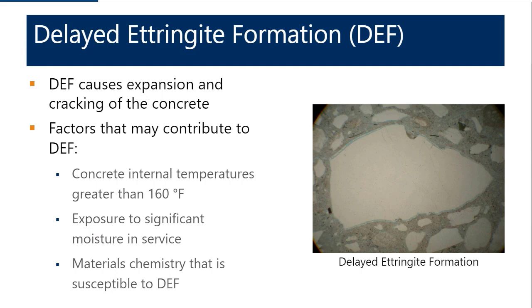So if temperatures exceed the specified limits, usually the next steps are to evaluate the risk of DEF. And that can be done by evaluating the materials chemistry or through doing petrographic analysis, where you actually look at samples of the concrete under a microscope, which is actually what this photo is from, and determine if DEF has happened or if there's indicators that there's a risk of DEF happening in the future. So it's not necessarily a deal breaker, but it does require further analysis.